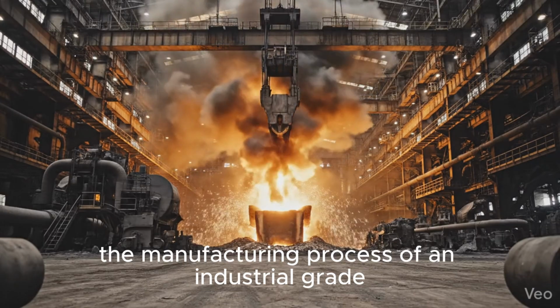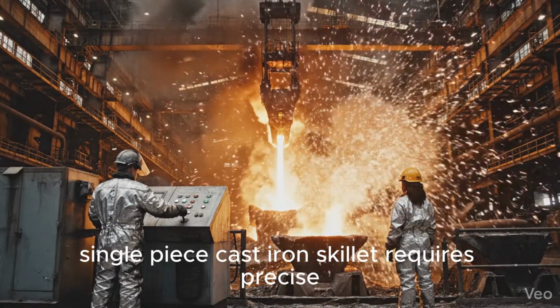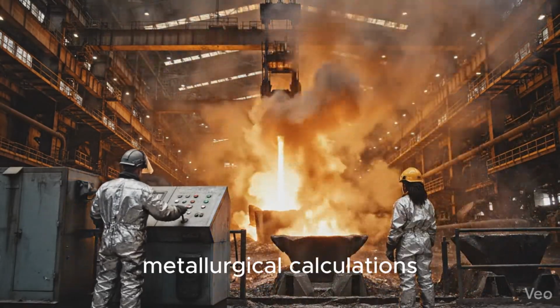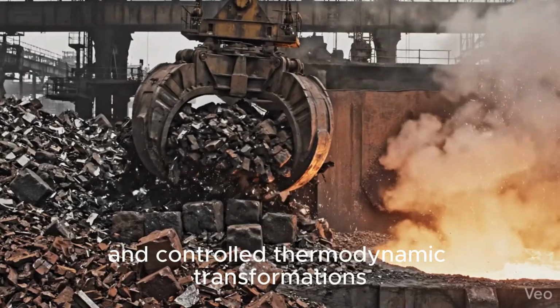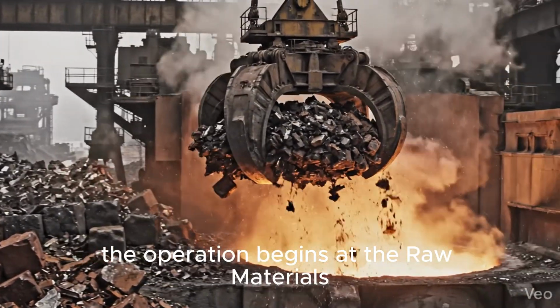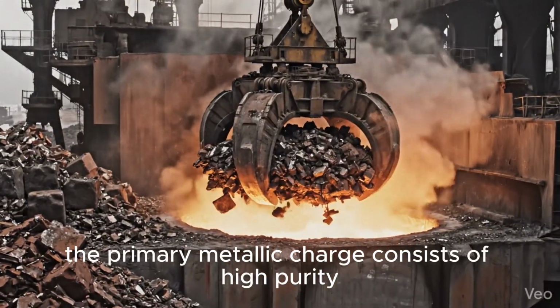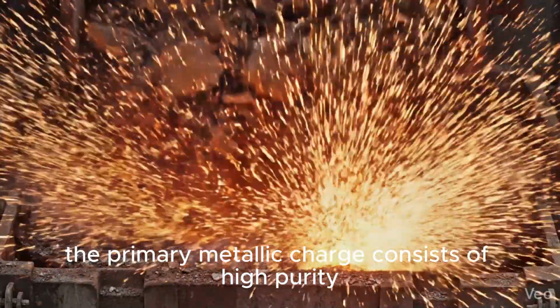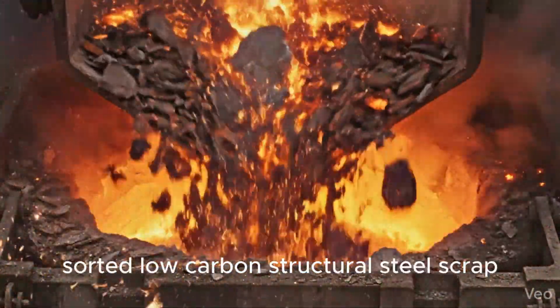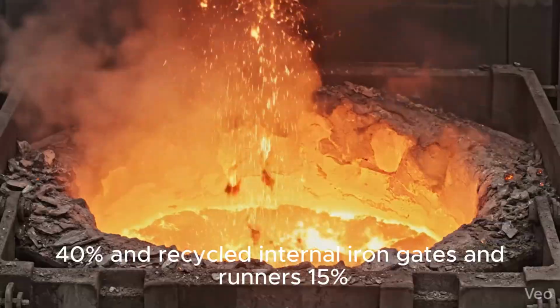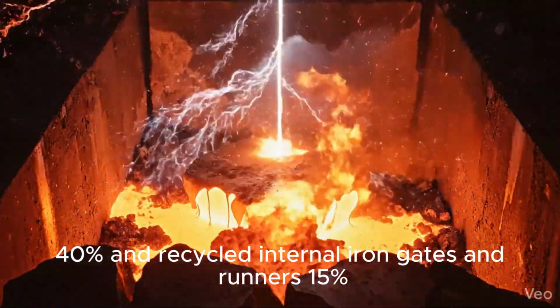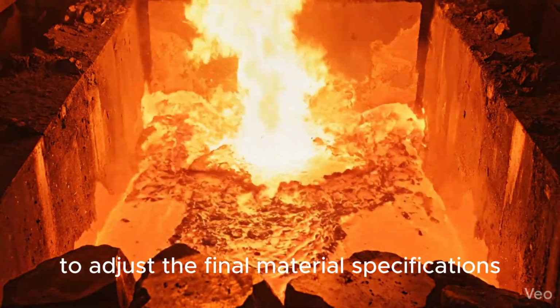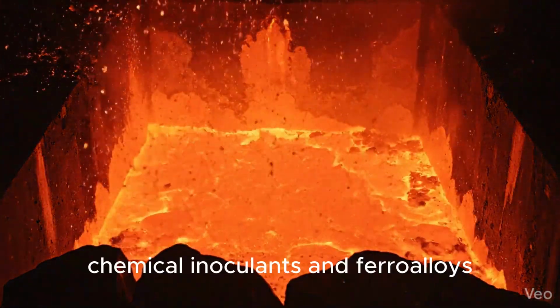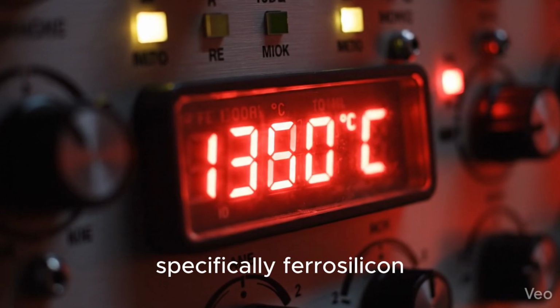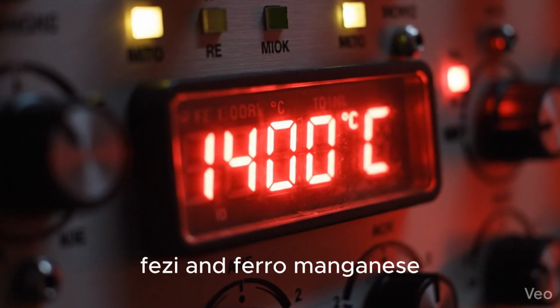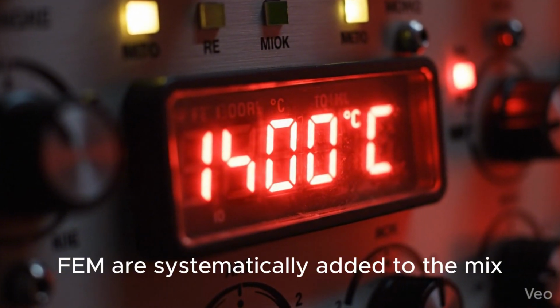The manufacturing process of an industrial-grade, single-piece cast iron skillet requires precise metallurgical calculations and controlled thermodynamic transformations. The operation begins at the raw materials automated stockyard. The primary metallic charge consists of high-purity pig iron, 45%, sorted low-carbon structural steel scrap, 40%, and recycled internal iron gates and runners, 15%. To adjust the final material specifications, chemical inoculants and ferroalloys, specifically ferrosilicon, FeSi, and ferromanganese, FeMn, are systematically added to the mix.